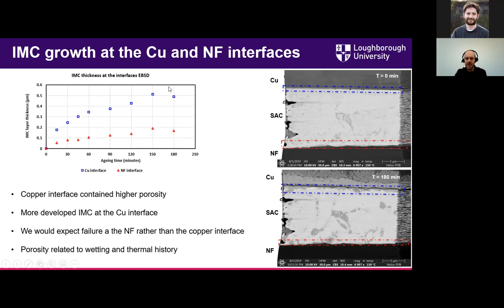And we also start to see coarsening of the precipitates later on during the thermal aging. So based on this, we'd expect a failure in the nanofoil rather than the copper interface, as the nanofoil formed a much thinner layer of intermetallics. And yeah, I think that's probably as much as we go into on this one.